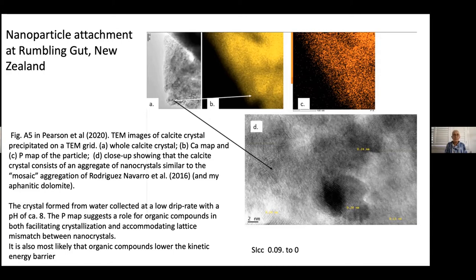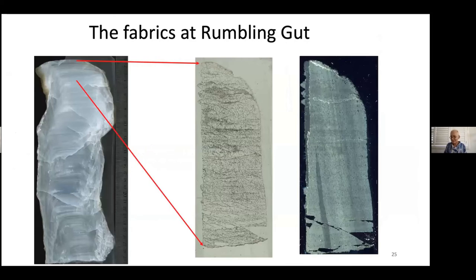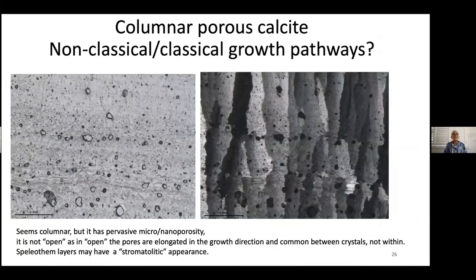nanocrystals can precipitate from water collected at a low drip rate with a pH of 8. And Adam just told me that the saturation is very low. So this could happen even at very low supersaturation. It's probably just a way to decrease the energy of nucleation and growth. Now, what's the fabric? The fabric is columnar porous. It's full of tiny little pores, again, between the crystals, not within. So that's why it's a different fabric. And it probably grows through different mechanisms, maybe not just one. Maybe it could grow by a classical way and a non-classical way. So columnar porous, non-classical, classical growth pathway, and what's the implication for you who are studying paleoclimate, looking at trace element distribution?